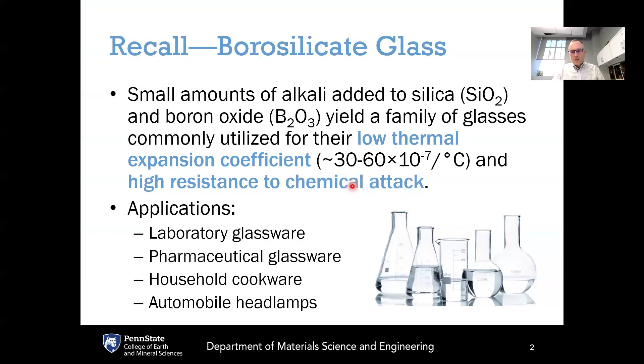Borosilicate glasses were first introduced back in Chapter 1. They were initially invented as a means to lower the thermal expansion coefficient of silicate glasses compared to sodalime silicate, while still being meltable at reasonable temperatures. A large portion of the network modifiers, sodium and calcium, get replaced by boron oxide B2O3, which is a network former rather than a network modifier, but it has fewer bonds — each boron has three bonds instead of four for silica, and each of those bonds is weaker.